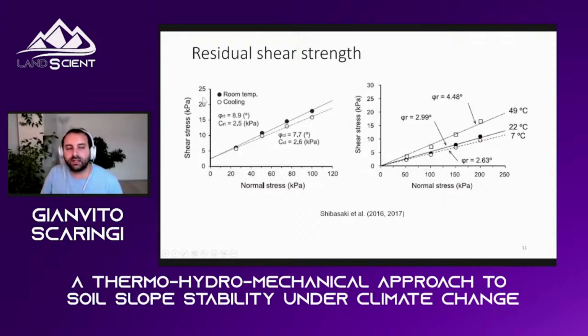This is a natural clay containing smectite, and on the right, they used a commercial calcium bentonite to better evaluate the behavior on a pure material. They made ring shear tests at different temperature. In particular, the black line here shows tests conducted at room temperature, 20 degrees, 22 degrees in their case. They did it when it was warm in the lab.